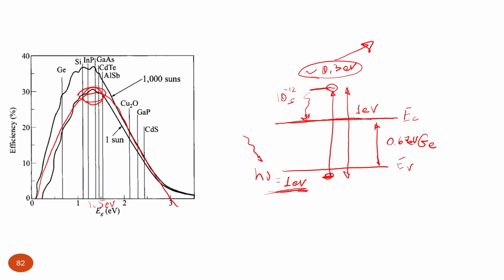So the best materials for photovoltaic application, here are some examples for inorganic semiconductors: indium phosphide, gallium arsenide, and cadmium telluride. But at the same time, silicon is not far away, and silicon is an abundant material, and technology is developed quite well for processing silicon semiconductors. It's cheap, much cheaper than any of these other solar cell semiconductor materials.